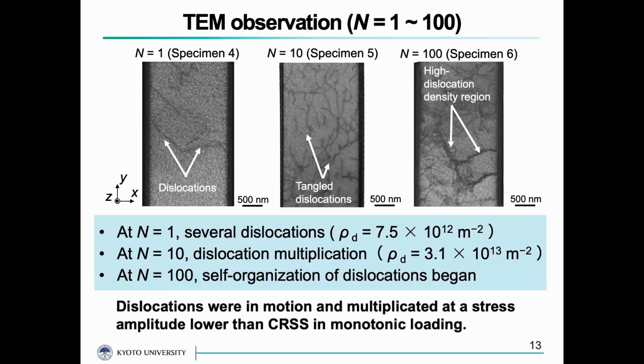Based on this result, dislocations were in motion and multiplied at a stress amplitude lower than CRSS in monotonic loading. Repeats of microscopic movement of dislocations would increase the opportunities for cross slips or dislocation interactions, which are considered to contribute to dislocation multiplication.